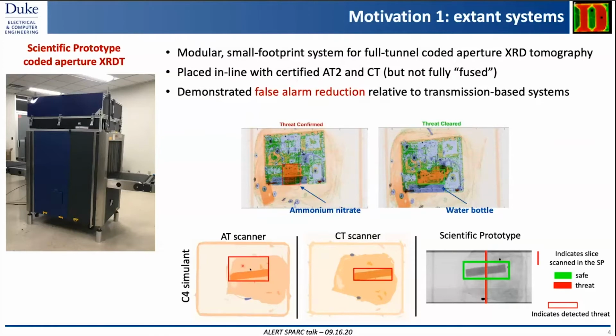But one example that we thought was particularly relevant, I showed down here on the bottom, an artistically blurred version of some data coming out of an AT scanner and a CT scanner. And the point of interest is that in this particular bag, there was a block of C4 simulant, which was by all rights correctly identified as a potential threat in the AT and CT systems. But when we scanned it in the scientific prototype system, we were able to identify that this block of C4 simulant, in fact, was not an explosive based on its X-ray diffraction signature. And so this just highlights the demonstrated false alarm reduction capabilities that diffraction provides relative to conventional transmission imaging systems.